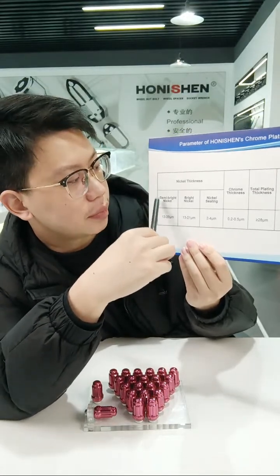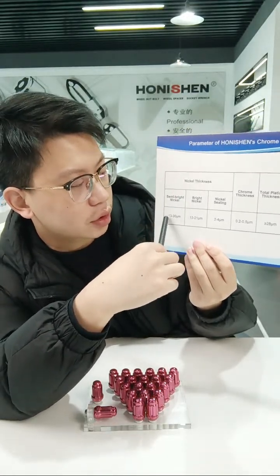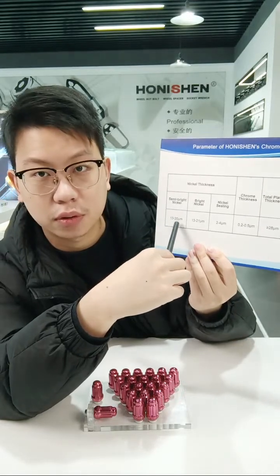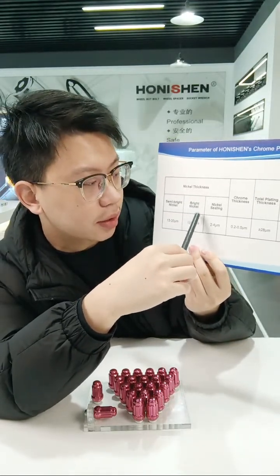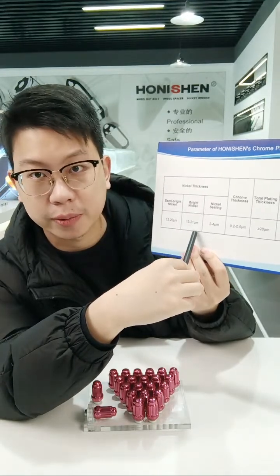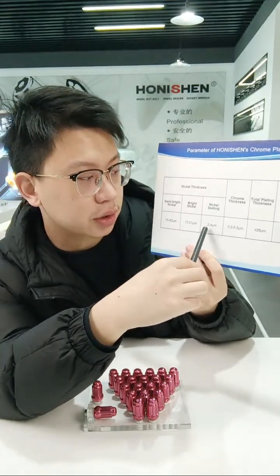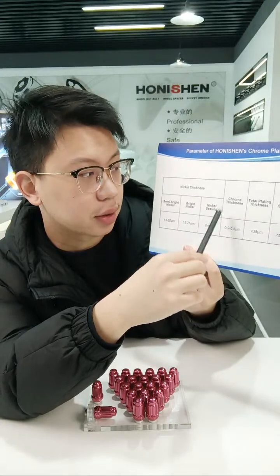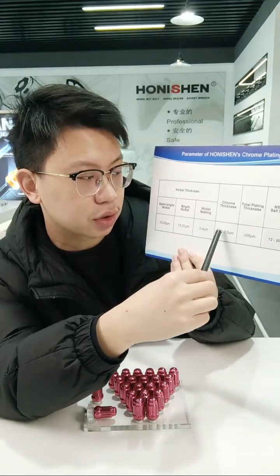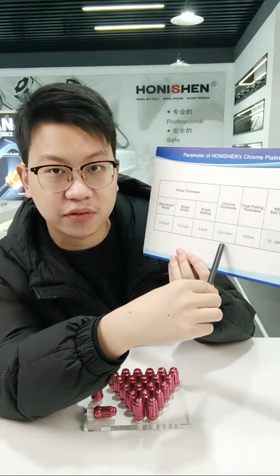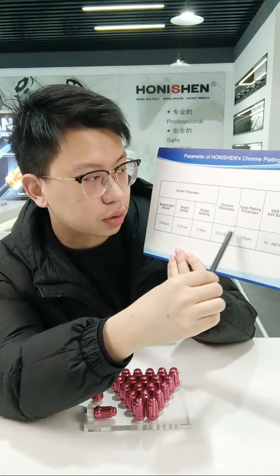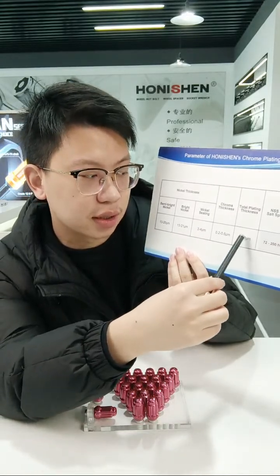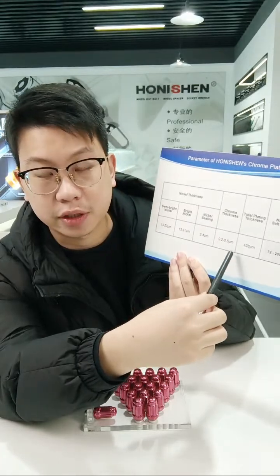And next we will see the standard for the electroplating layer. The semi-bright nickel layer should be 13 to 20 micrometer, and the bright nickel layer should be 13 to 21 micrometer. The nickel sealing should be 2 to 4 micrometer, and the chrome thickness should be 0.2 to 0.5 micrometer. The total plating thickness should be more than 28 micrometer.